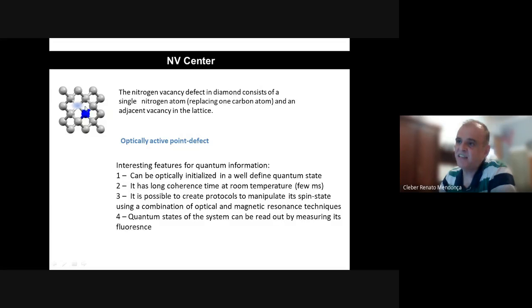So basically, an NV center, which stands for nitrogen vacancy center, is a defect in diamond in which the nitrogen, as you can see by this blue sphere here, replaces the carbon atom and is adjacent to a vacancy. So that's this defect that's called the NV center. The good thing about that for quantum information is that you can optically initialize the defect center. It has a long coherence time. You can create protocols to manipulate the spin. So it's very interesting for quantum information people.